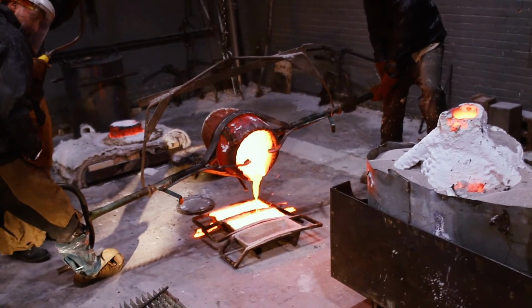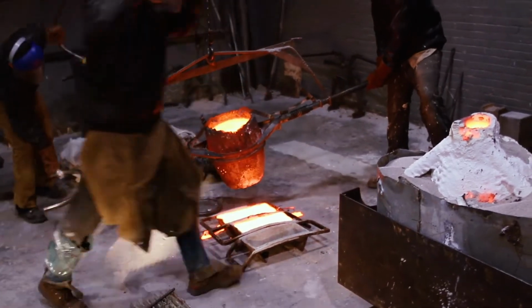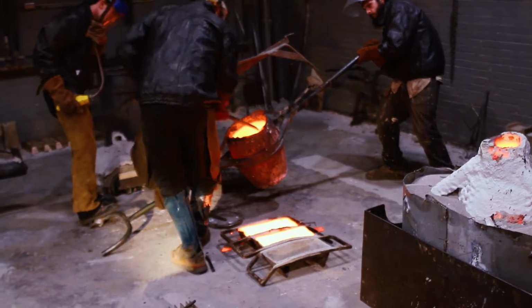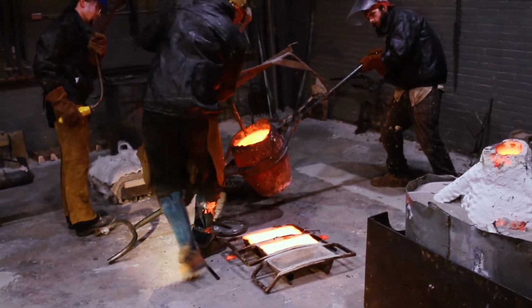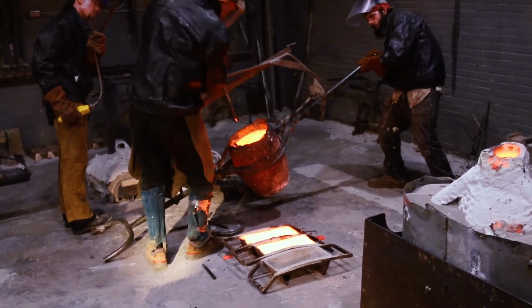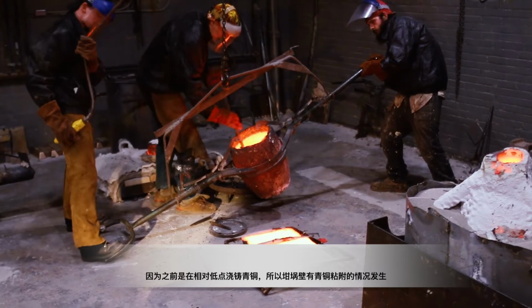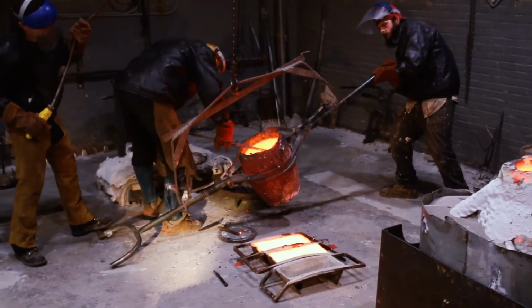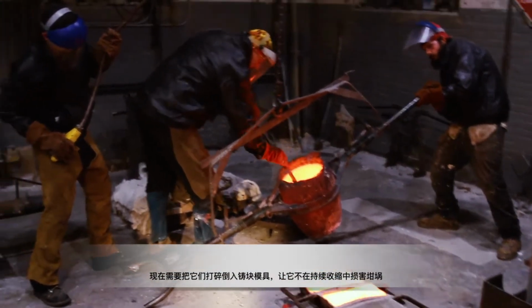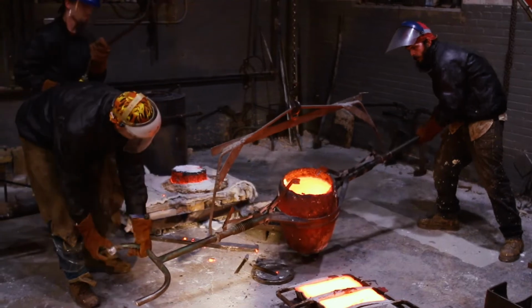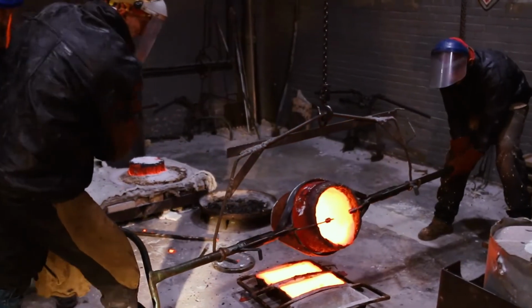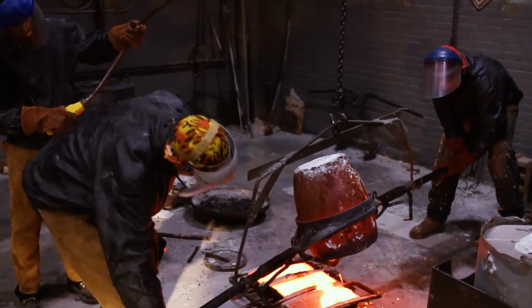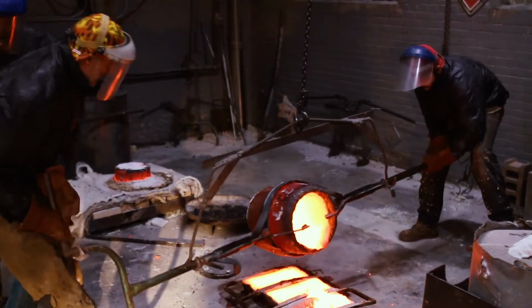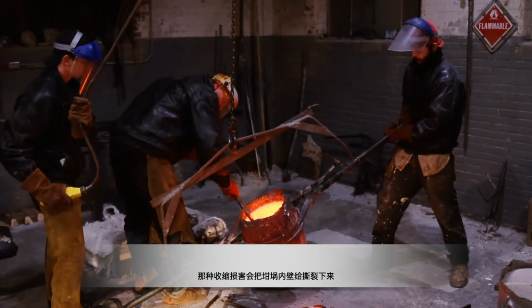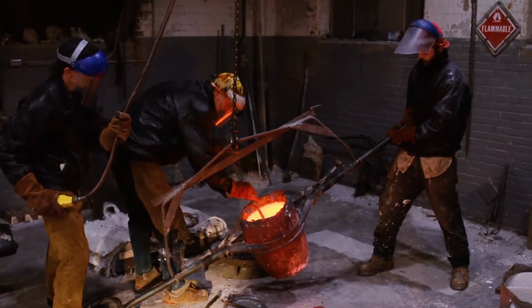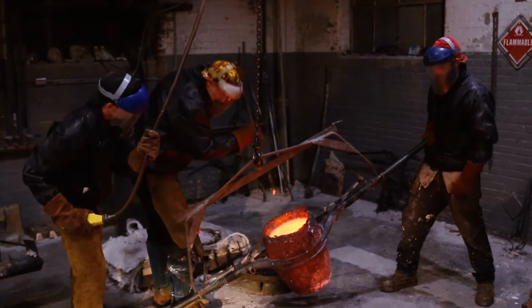And here we've poured a couple big ingots. And the metal itself, since I'm pouring at the coldest point possible, so that it shrank the most in the crucible, it's also sticking to the walls of the crucible. So right now I'm breaking up the metal and trying to get it out of the crucible, so that it doesn't damage the crucible as it continues to shrink, and it'll just tear a layer, like 1/16 of an inch of the inside of the crucible with it as it shrinks.